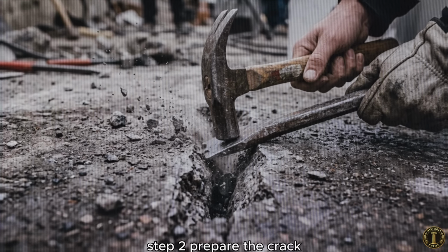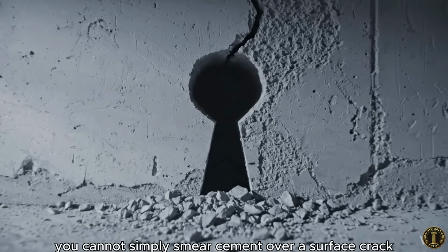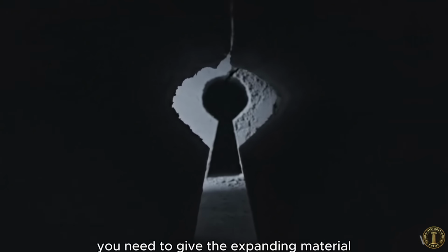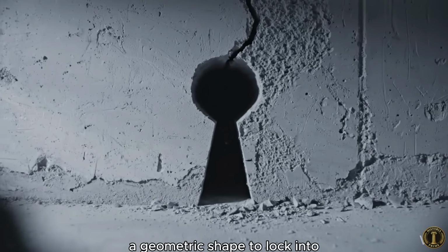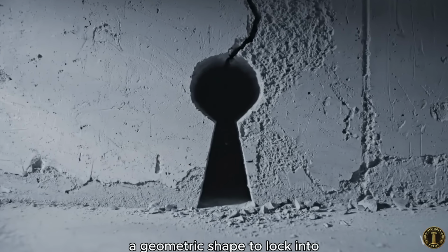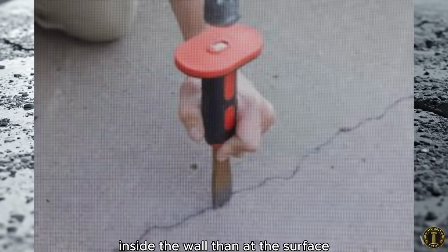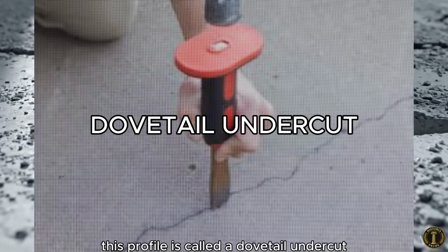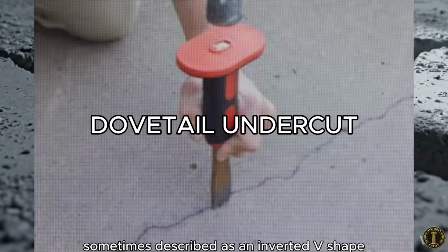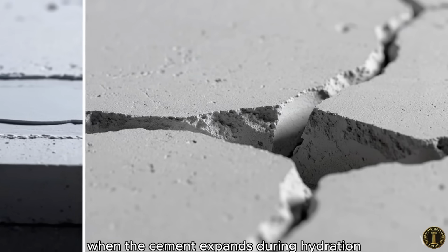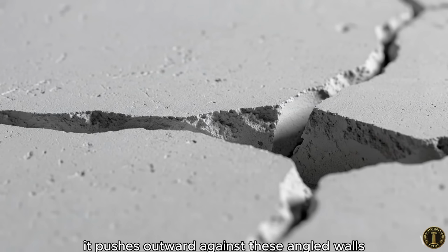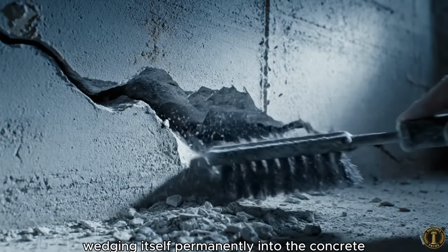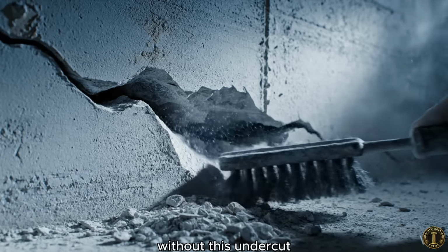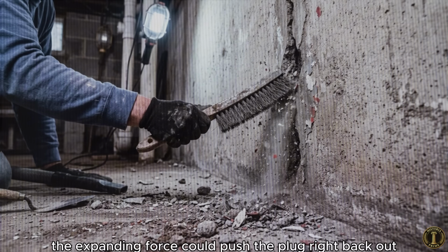Step 2. Prepare the crack. You cannot simply smear cement over a surface crack. You need to give the expanding material a geometric shape to lock into. Take a cold chisel and hammer and carefully widen the crack so that it is slightly wider at the base, inside the wall, than at the surface. This profile is called a dovetail undercut, sometimes described as an inverted V-shape. Think of it as a keyhole. When the cement expands during hydration, it pushes outward against these angled walls, mechanically wedging itself permanently into the concrete. Without this undercut, the expanding force could push the plug right back out.